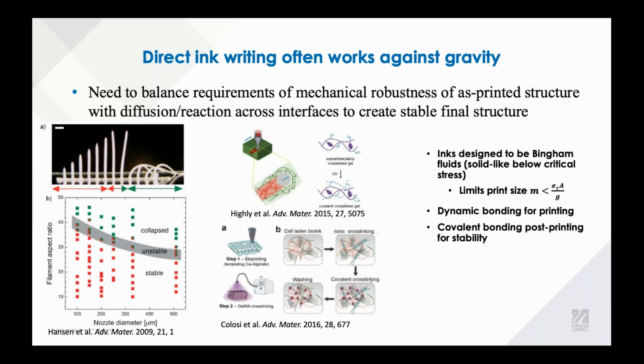Another thing that we think about in direct ink writing, especially in trying to fabricate things like scaffolds, is there's often this desire to have dynamic bonding during printing. You can see both of these examples. There are these ionic or supramolecularly cross-linked gels, and that facilitates having bonding across the layers so that you don't have that Z-strength consideration quite as much. And then after a structure is printed, there will be some process, often a UV process, in order to covalently bond post-printing for stability.